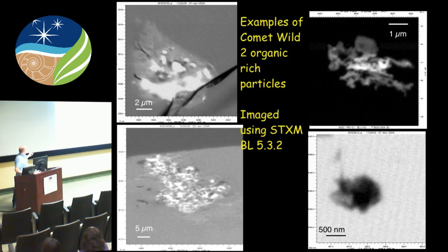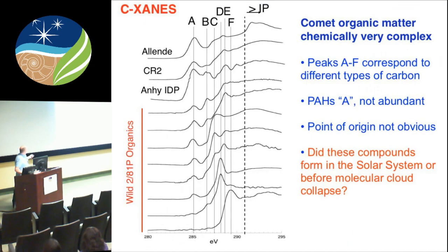Bottom line is we collected carbon spectra on all these different particles, and we compared this with an interplanetary dust particle here, a primitive chondrite here, a more thermally evolved chondrite there. And you see a lot of complexity. That's all I need to tell you at this point. Nothing really systematic seems to be occurring here. There's a lot of chemical complexity. Here I've highlighted a number of different peaks that correspond to different functional groups. So the question is, how did these compounds form in the solar system or prior to molecular cloud collapse?